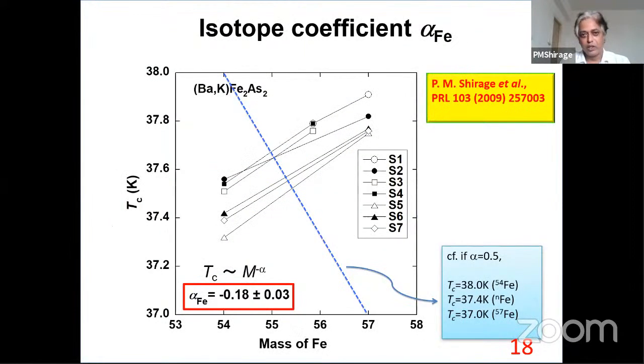Another contribution which I made in this field of physics is the isotope effect. What is the isotope effect? It is when we vary the isotopic mass of the material in the superconductor, then TC will change. The higher the phonon frequency, the higher the TC. For example, for this iron, barium, potassium, iron 2 arsenic 2 material, if it has isotopic mass 54, it should show TC around 38 Kelvin. If we change the isotopic mass from 54 to 57, then TC will decrease, because as the weight of these atoms increases, the phonon frequency decreases, and as a result TC decreases.